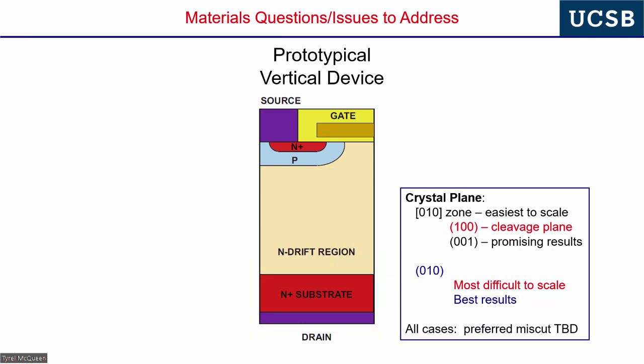The next thing, the epi grower, and that would be me, says I want to have systematic miscut studies, okay? So I want to know the intentional miscut of the substrate because that affects the step terrace spacing and whether I'm in step flow growth or layer by layer growth, okay? And then this consumes a lot of boule, okay? Because these have to be wire sawed on a precision goniometer. And then also in an intermediate step, the CMP polishing has to be developed.